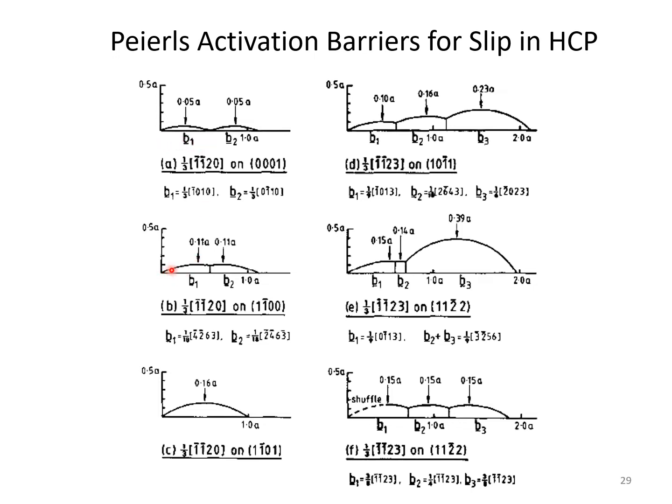But for the prism slip, it's very difficult to do that because this is a metastable state, and it's so much easier just to slip down. And so what you tend to get with prism slip is no splitting of the dislocations. You never see any evidence of any partial dislocations here. And if it's pyramidal slip, a slip on a pyramidal plane, and again, you watch the videos, you'll see this, there's absolutely none at all. It's a higher energy barrier that has to be gone over.